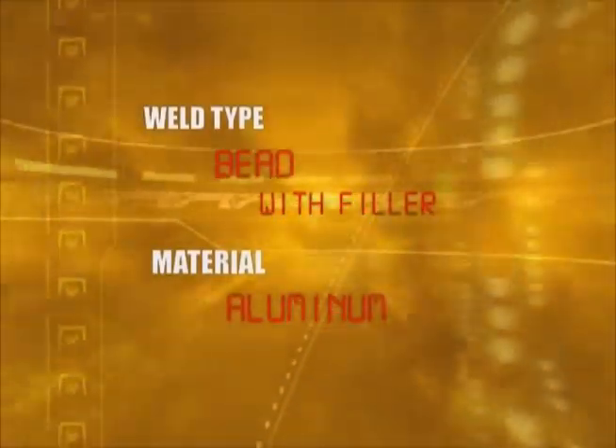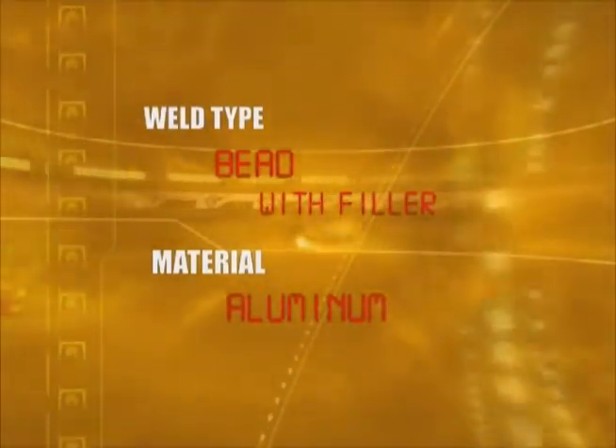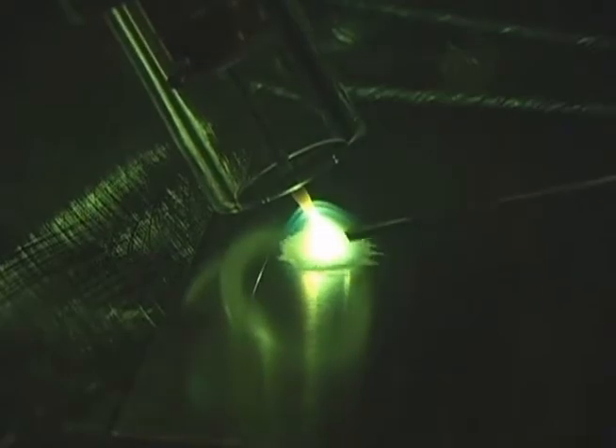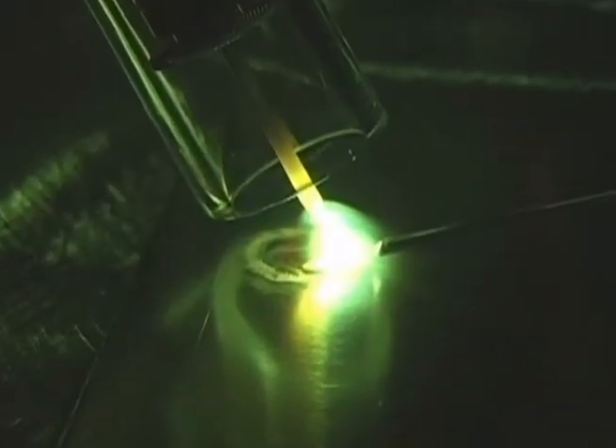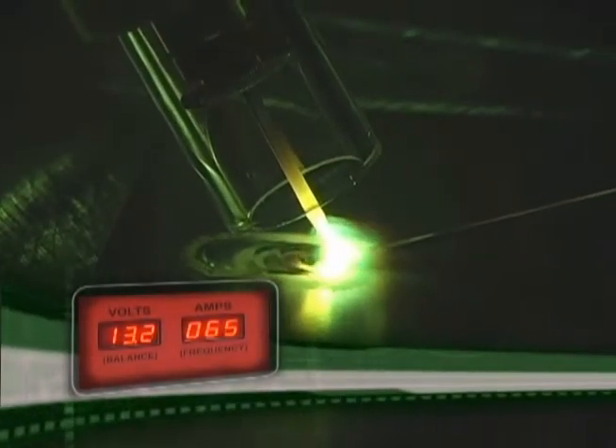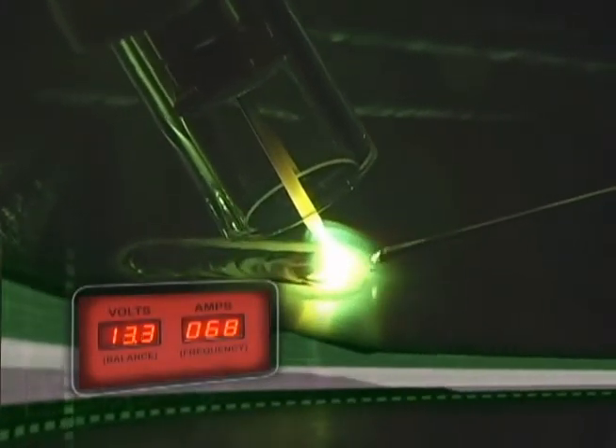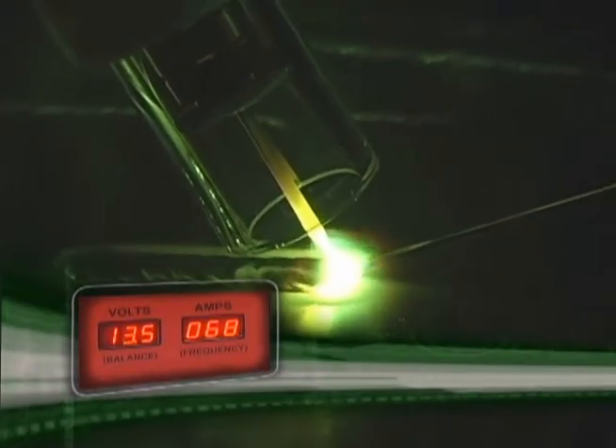Once you have mastered a bead without filler, then you can try a bead with filler. Depress the pedal to start the arc. You need to look for the shiny puddle in the middle of the dull area. That's the molten puddle. Once you have the molten puddle, you begin to dab the filler in the leading edge of the molten puddle just like steel.